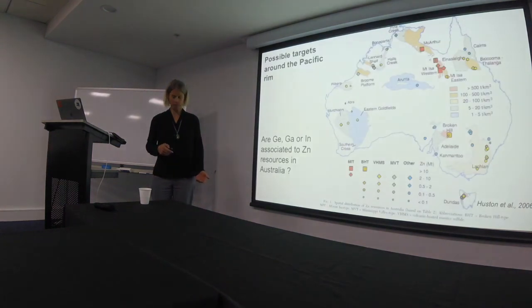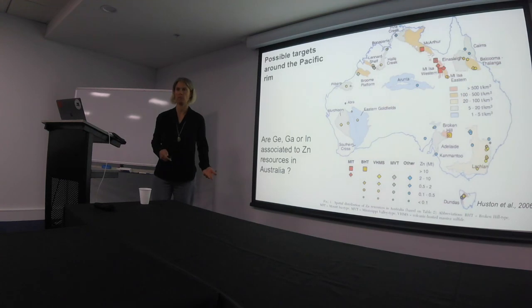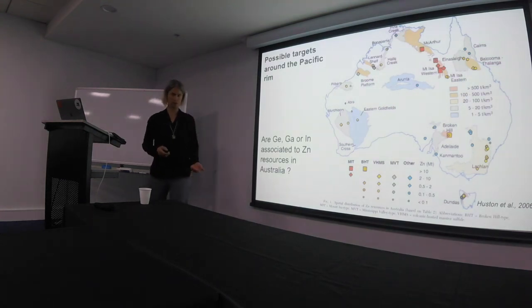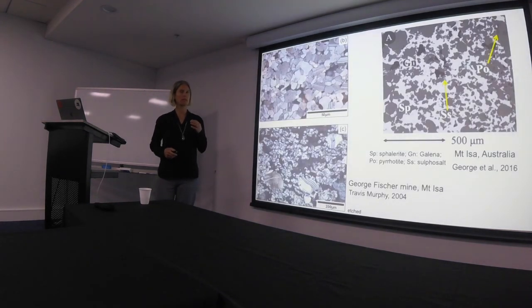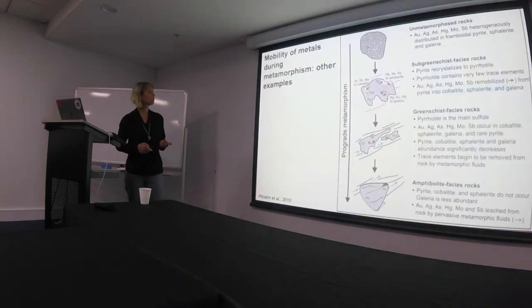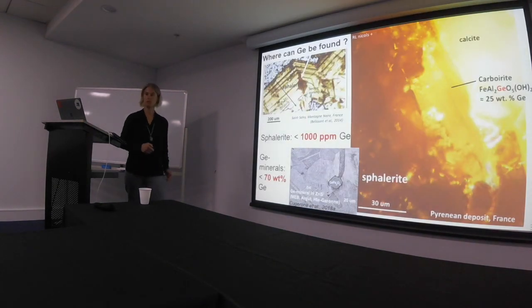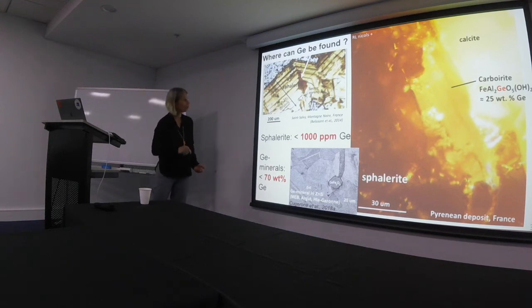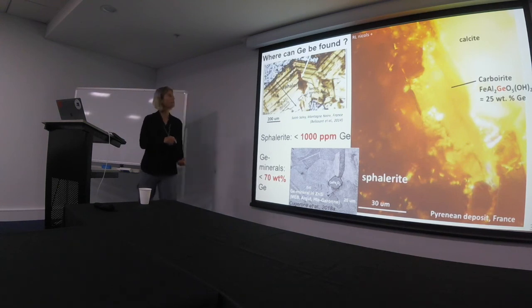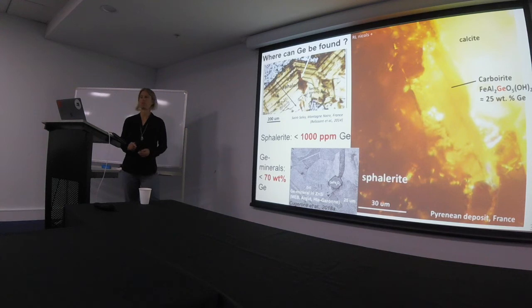I think the fine grain material, which is only around 10 ppm, is not worth it, and it is actually not exploited currently. Most of the lead zinc deposits that are exploited for germanium are, like I showed first, can we go quickly back, the very first slide, that one. Most of the germanium exported nowadays is in sphalerite which is properly zoned, with a homogeneous concentration around 1,000 to 3,000 ppm, and it is extracted from this kind of sphalerite. The germanium is not extracted from these orogenic deposits.